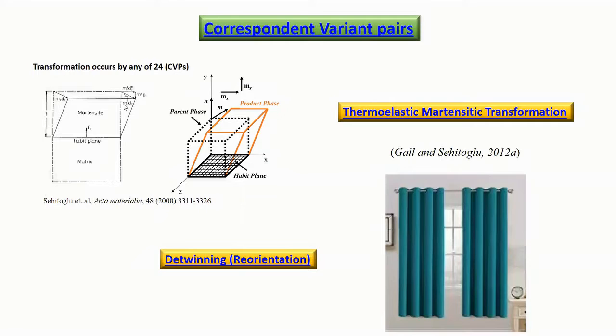Okay, so now when the conversion from austenite to martensite is over, this martensite initially forms in a twinned condition, right? And to draw an analogy, I'm just showing you the picture of this curtain. So what happens is that now with the application of stress, these twins can spread themselves, right? So this is called the reorientation or detwinning, where you can think of stretching these curtains, and that is how it will generate the amount of strain. It is getting a different shape.